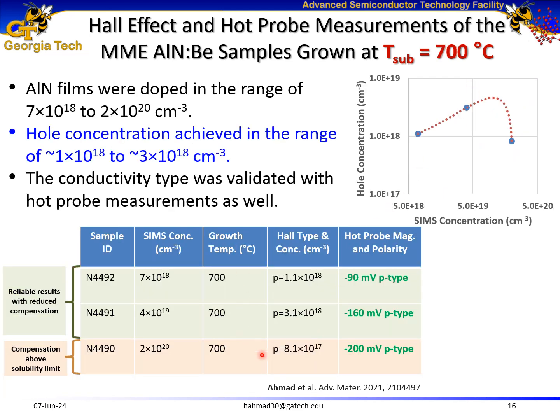I also grew beryllium-doped aluminum nitride at 700 degrees C growth temperature and achieved even higher Hall concentration of 3 into 10 to the power of 18 per centimeter cube. And the conductivity type was also validated from hot probe measurements.